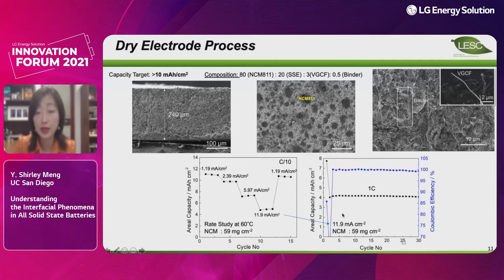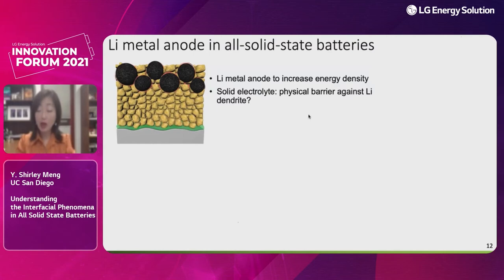In a more recent program, we successfully made NMC cathode electrodes through dry electrode processing with loadings exceeding 10 mAh/cm², using vapor-grown carbon fiber and special binders to achieve very good cathode material utilization. This is recent data from a preprint showcasing that high loadings are possible for NMC cathodes. The temperature is 60°C, but please note we have more than 10 mAh/cm² loading for the cathode. With the cathode-electrolyte interface more or less resolved, the challenge is enabling lithium metal anode.